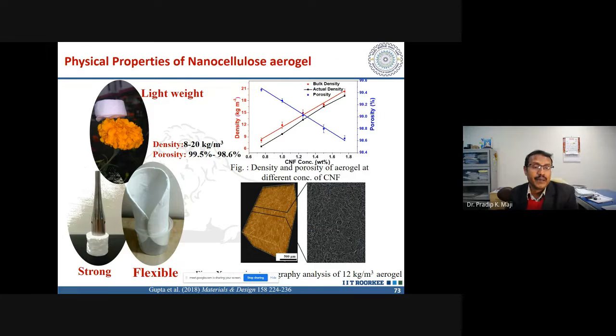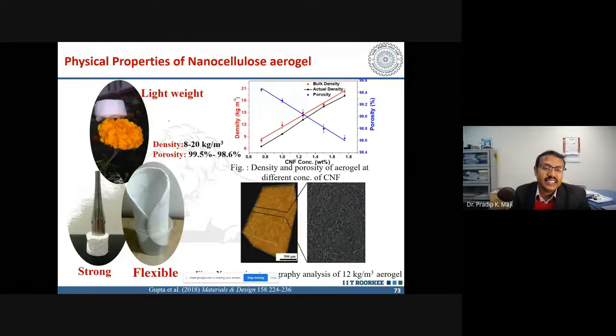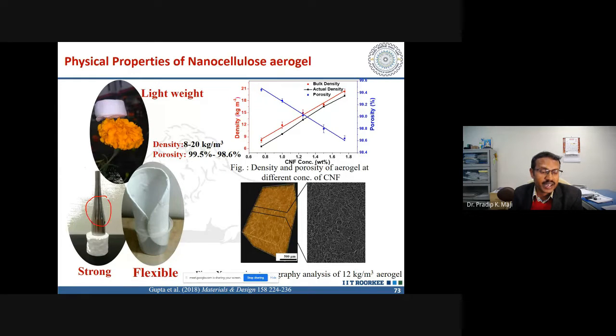And this is the prepared material. It is so light that it can stay on a marigold flower. You see, this is our material, and it is so strong that it can withstand almost 500 grams of weight. It is flexible, so it can be folded and put in a glass. The density is 8 to 20 kg per meter cube, and porosity is 99.5 to 98.6%.